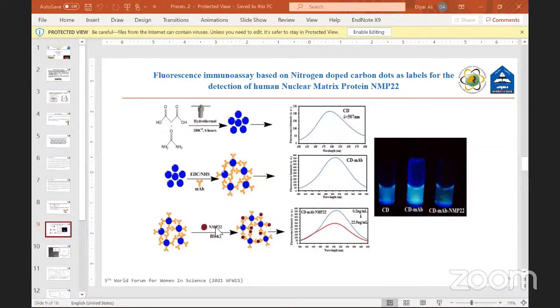Then we added our target, which is NMP, which makes a large particle, and the fluorescence was checked again by photo. It's clear the fluorescence decreases, and we also measured the fluorescence by instrument, and with different concentrations of our target, the fluorescence decreases gradually, or we can say the fluorescence is quenched gradually.